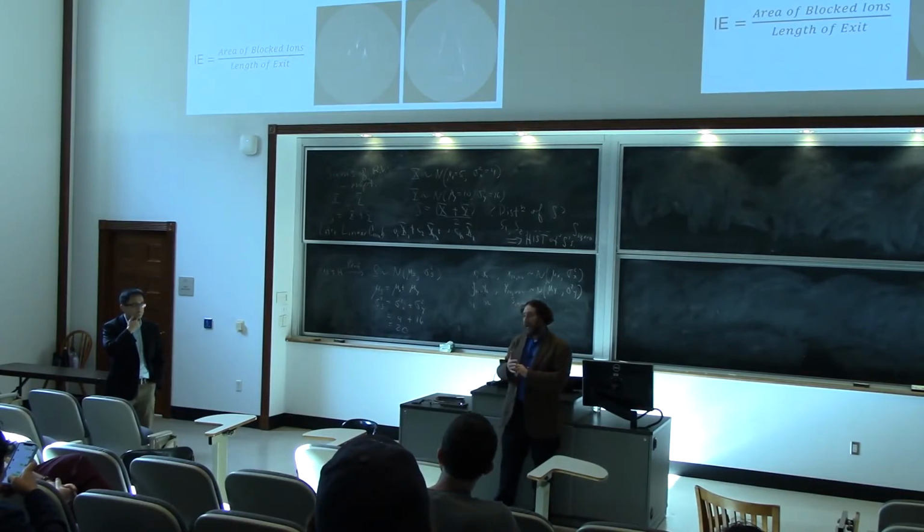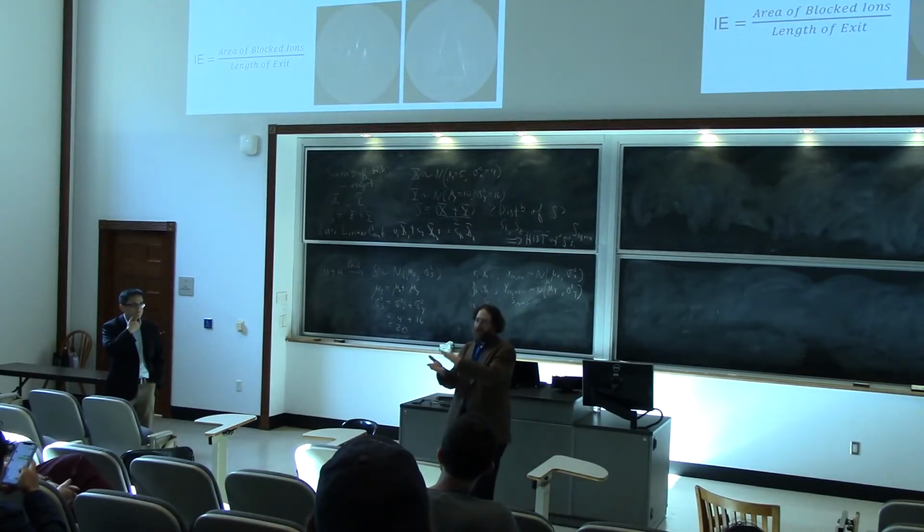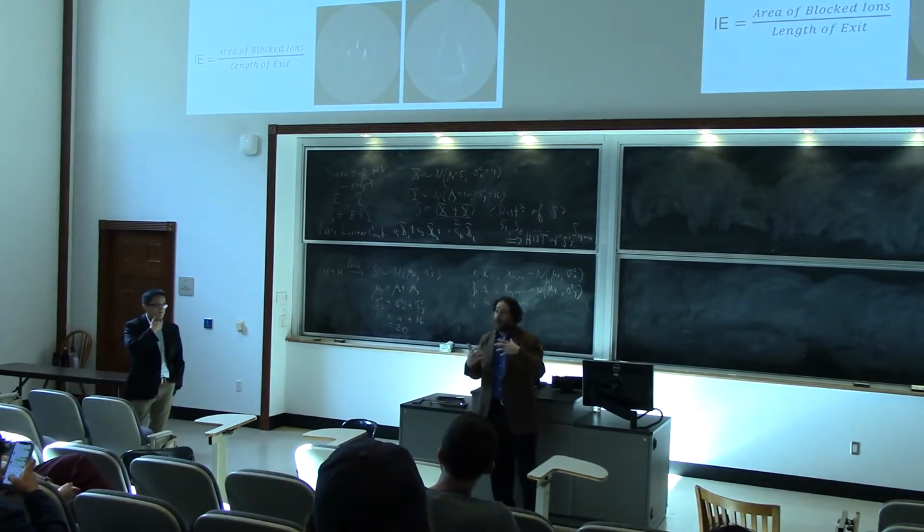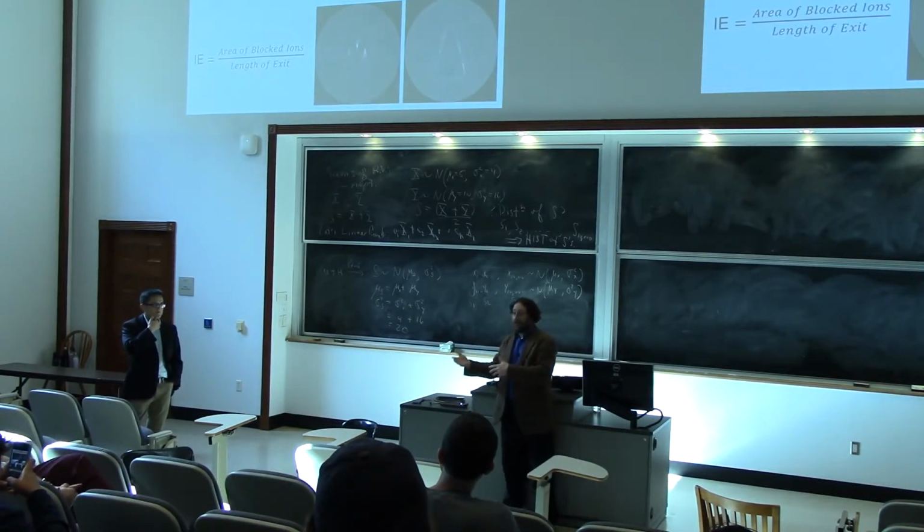And the second answer that I have for you is that when we redo our experiments with unstressed materials, so we don't apply mechanical stress, and we just put these closed pores and these other structures in there, and get the same result, it gives us confidence that our understanding of the mechanics is fair and it's not thermal phenomena.